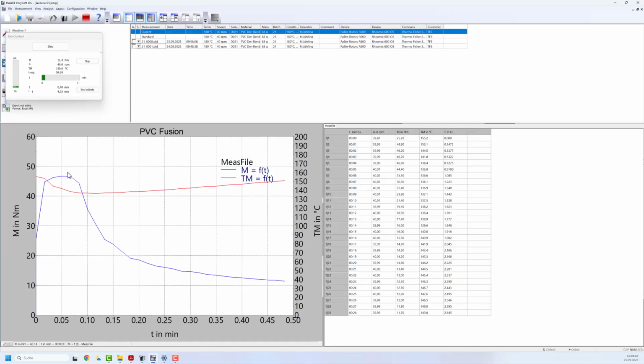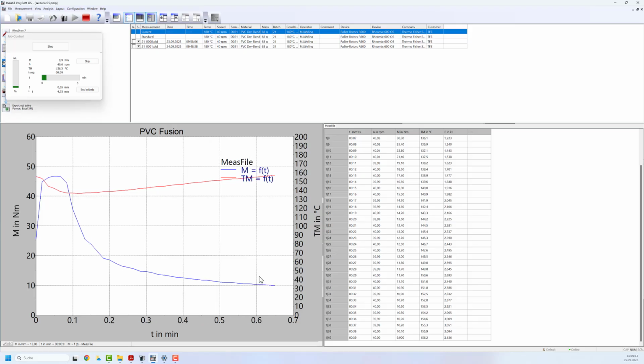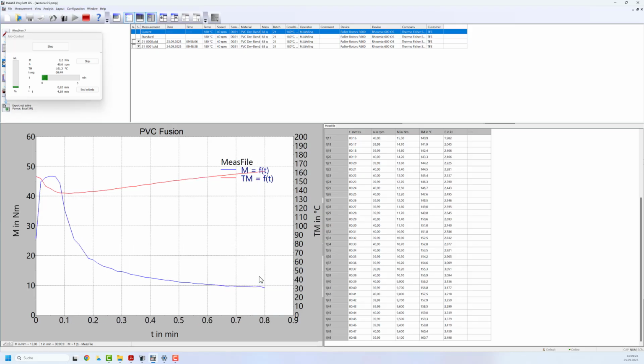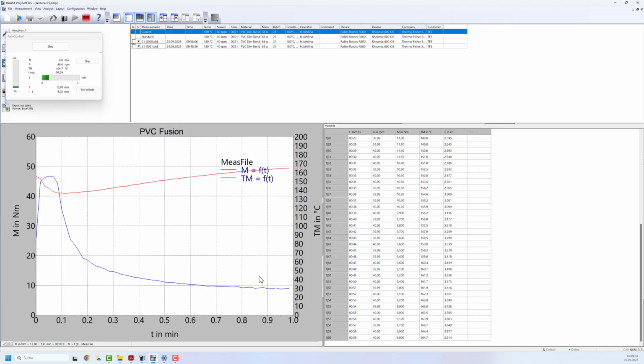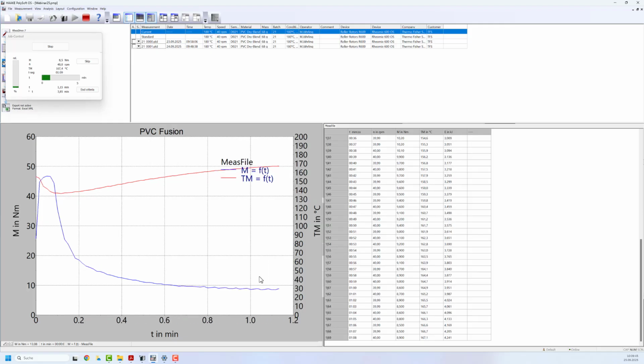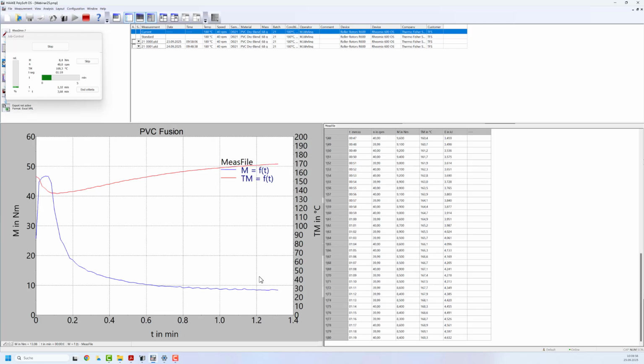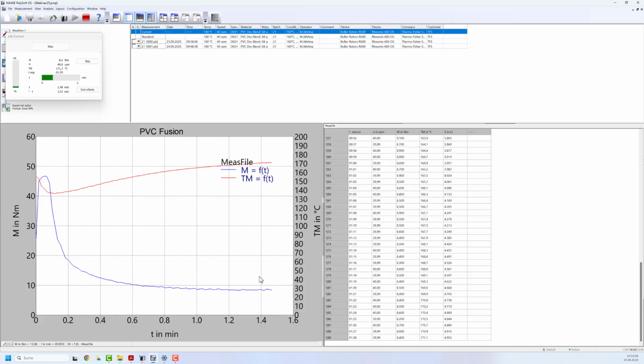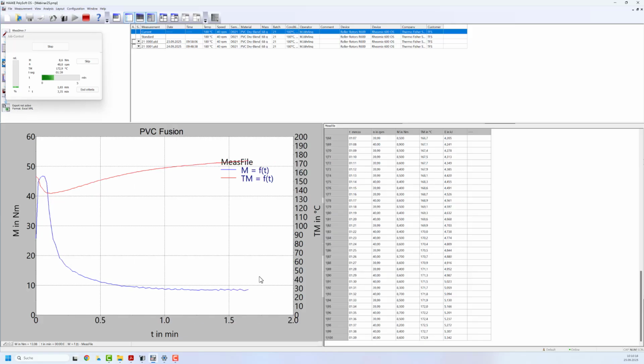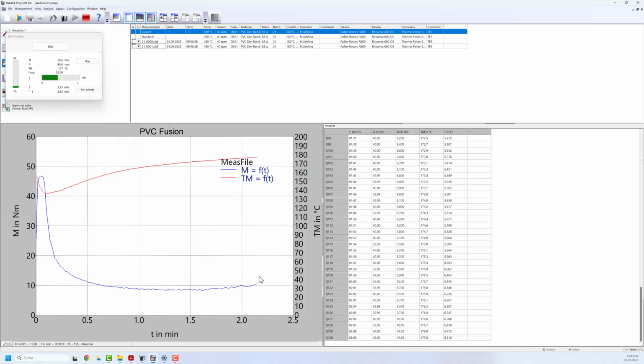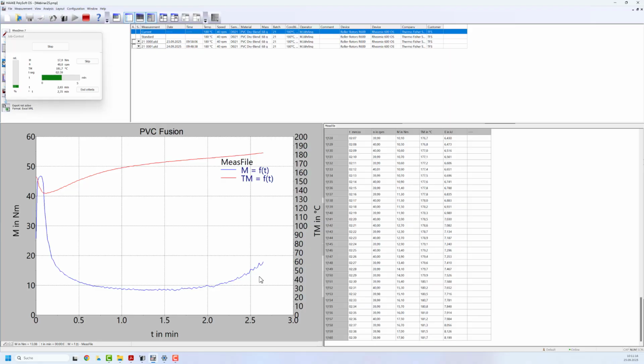If we now look at the curve, we see how the torque is going down. PVC powder is distributing in the mixer chamber. Now we can see that due to the shear and the heat inside of the mixer, PVC now starts to agglomerate, building areas of more fused material, which results in an increase of viscosity of my mix, and this we can see here in the rise of the torque.